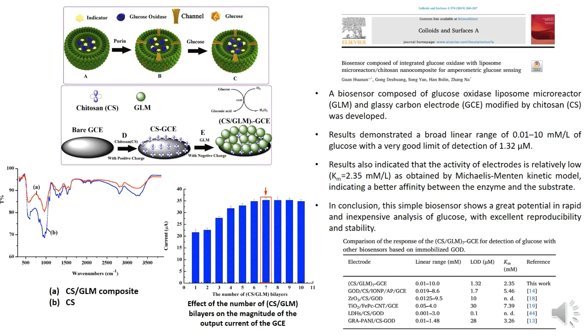The results of this study reflected a broad linear range of detection, starting from as low as 0.01 millimolar per liter up to 10 millimolar per liter of glucose, with a very good detection limit of as low as 1.32 micromolar. Results also indicated that the activity of the electrodes is relatively low, and so it has high sensitivity to glucose, as obtained by Michaelis-Menten kinetic model, indicating better affinity between the enzyme and the substrate. The authors concluded that this simple biosensor shows a great potential in rapid and inexpensive analysis of glucose with excellent reproducibility and stability.